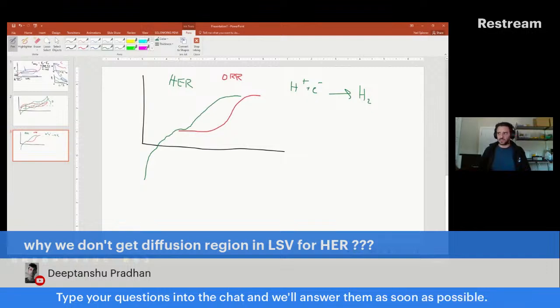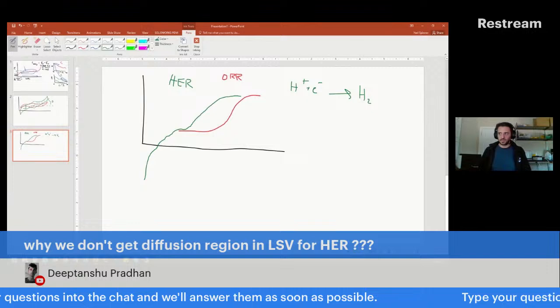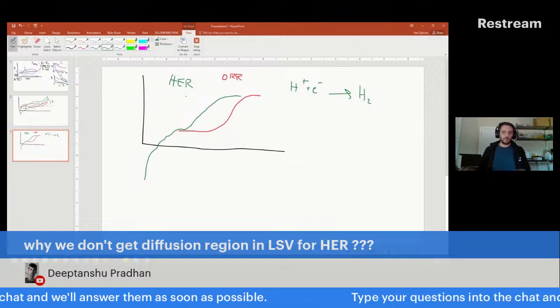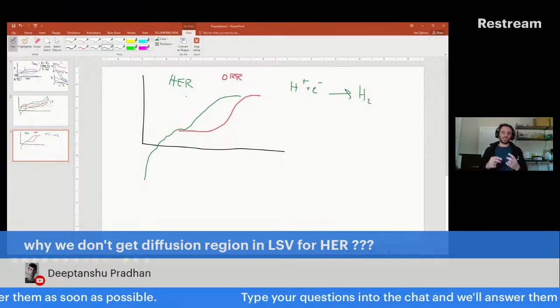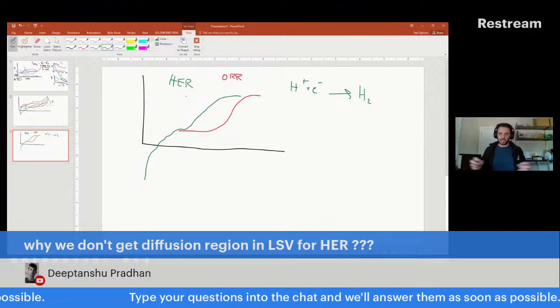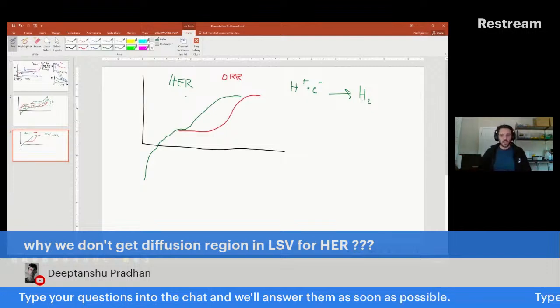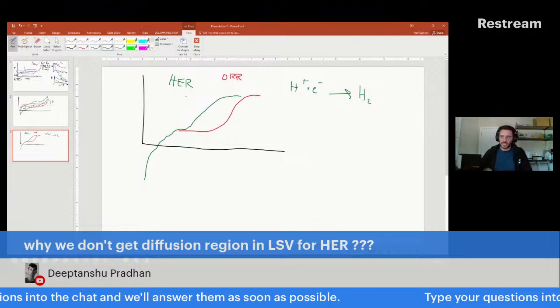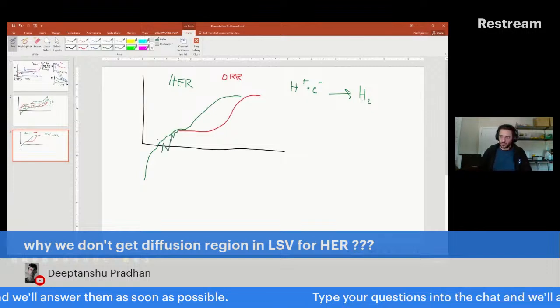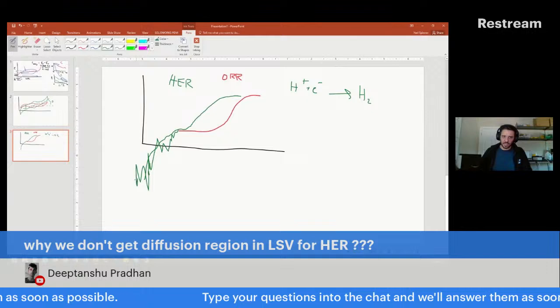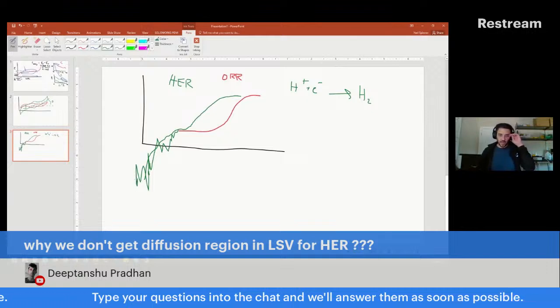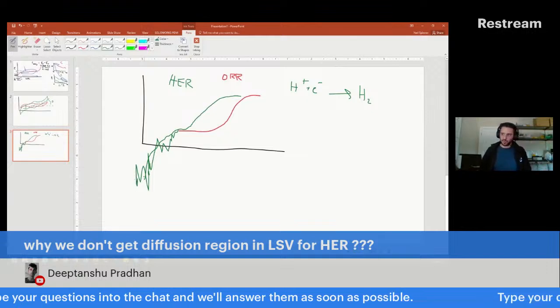It just becomes difficult a lot of times to do Tafel analyses and different kinds of analyses because the formation of gas on the surface breaks up the electrode-electrolyte interface, and it just makes the current data jump around sometimes. You can get kind of crazy results. So that's another reason why I think sometimes it behaves poorly.